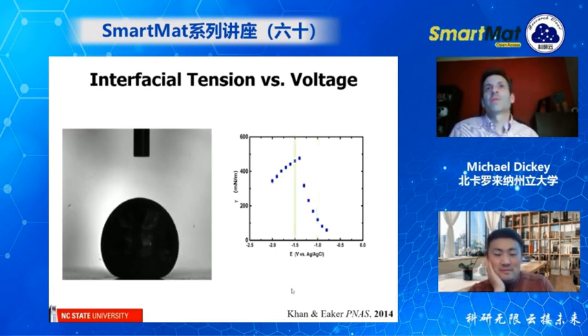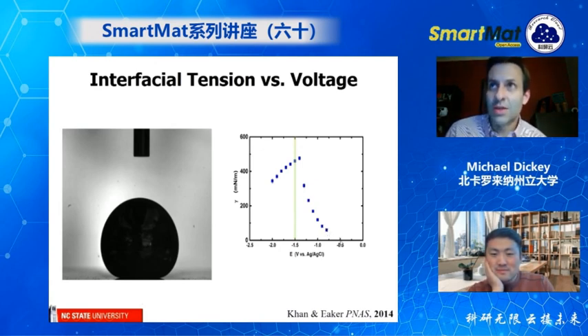So we're going from very large tension, like 500, and you can see it gets lower and lower and lower. And then at some point, it actually looks like it's going to go to 0. And that's exactly where we see the fractals. That's also exactly where we see that wire. If you form fractals, that means there's no penalty for forming more area. And that's essentially what we're seeing: as the tension gets lower and lower, right around this voltage, negative 1.5 to negative 0.5, that delta is about 1 volt. So that's why I said 1 volt. That's where we get this really low surface tension.